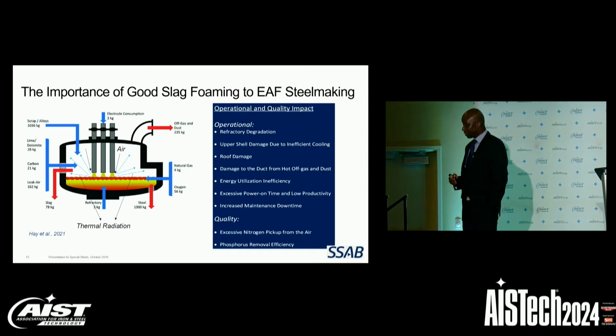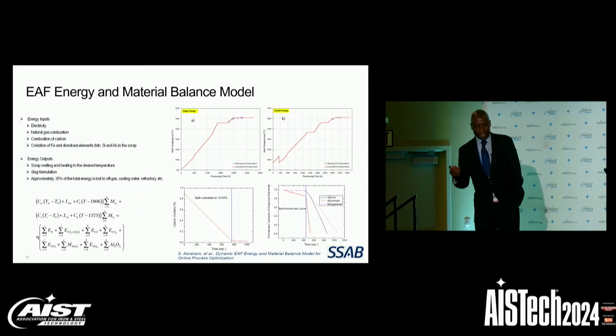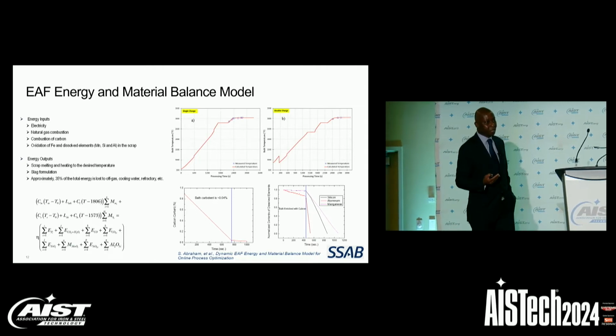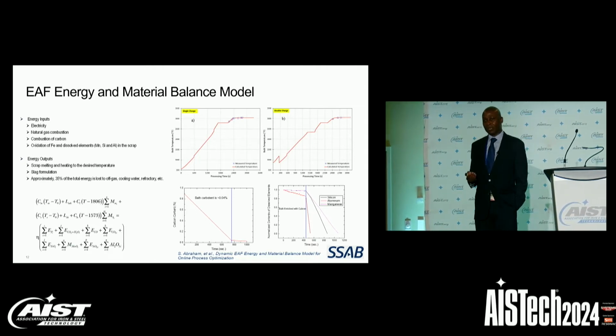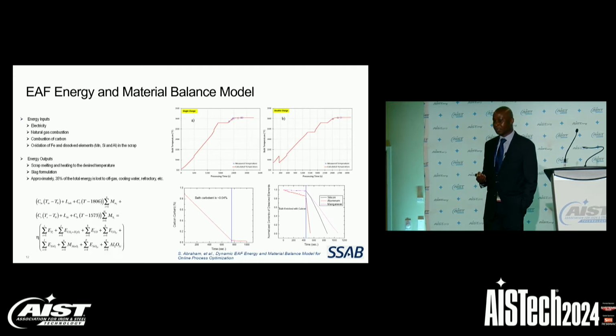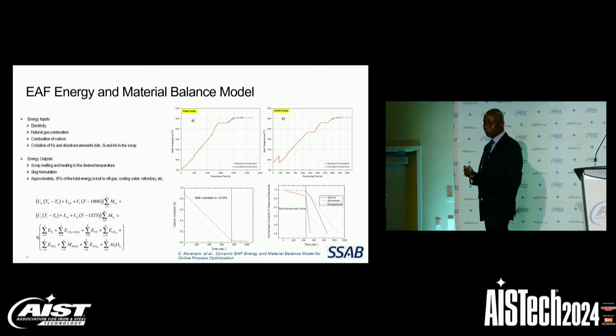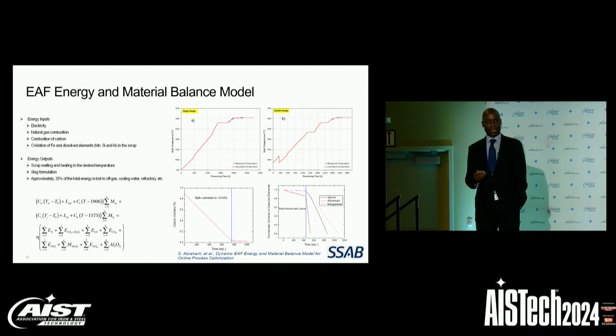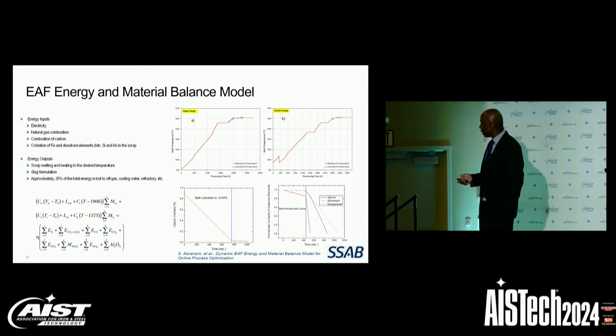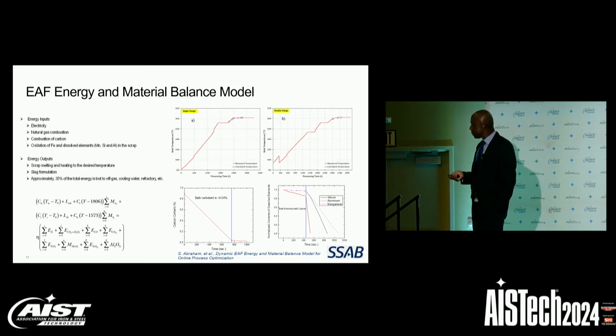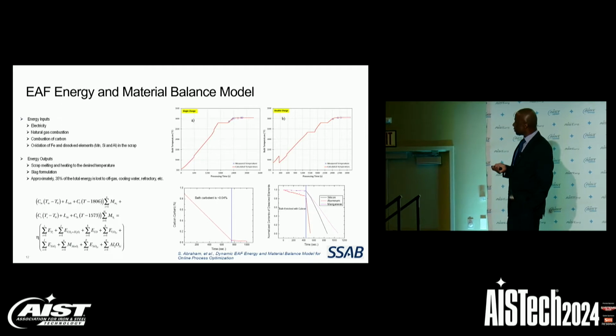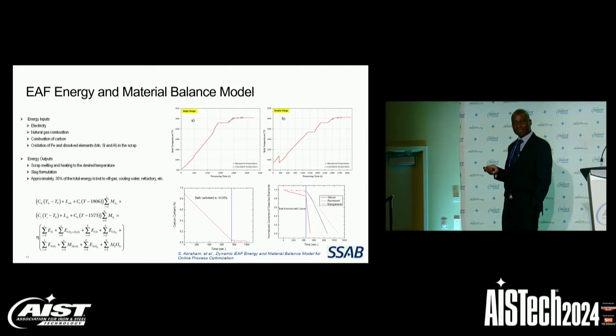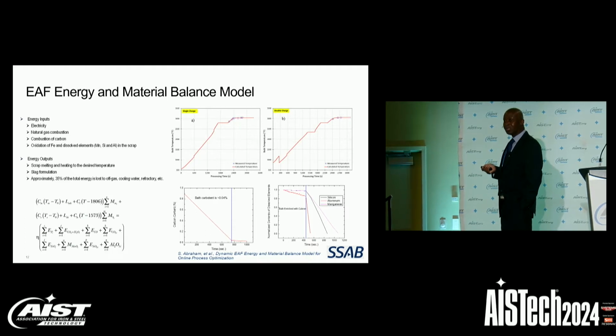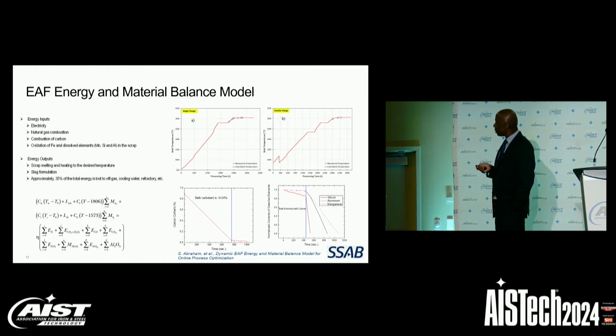So because of that, as a solution, we decided to develop an energy and material balance model to help the operators understand the state of scrap melting in the furnace. The energy inputs and outputs were systematically identified and quantified, resulting in a complex equation for predicting the temperature of the bath during scrap melting. The red curves that you are seeing here are the predicted temperature of the bath during scrap melting. As you can see, they are in good agreement with the measured temperatures that are represented by the open circles.